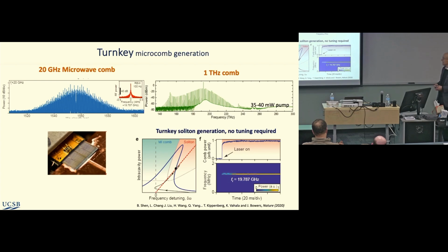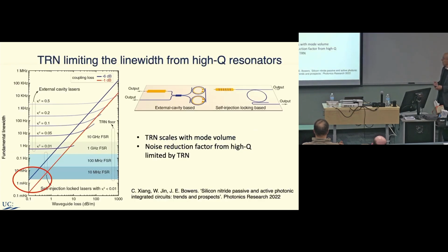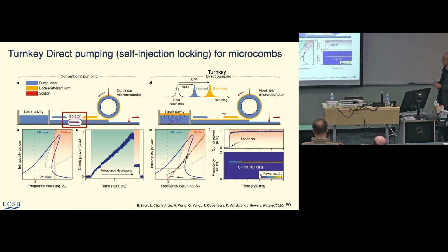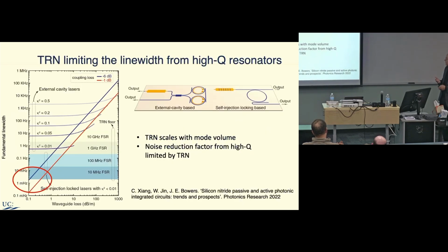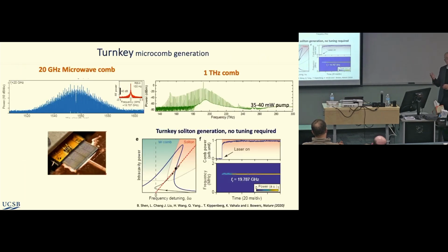And so we use this for a lot of things. One minor thing is we now use multiple rings together. If you use 3 rings in particular, I can tune the dispersion of that coupled cavity to be either positive or negative. Initially we're using these to generate bright solitons, but now we can, in the same device, generate bright solitons or dark solitons, either positive dispersion or negative dispersion. And that's really pretty interesting.